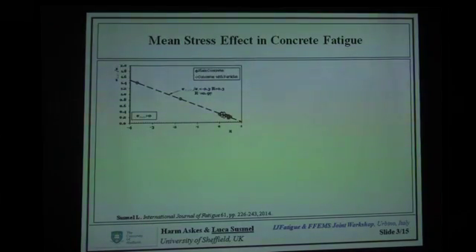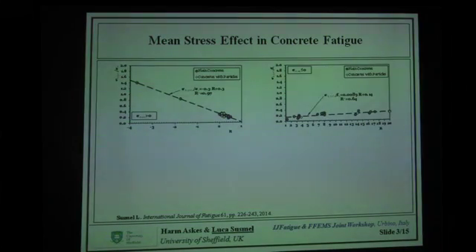If you start considering the high cycle fatigue behavior of concrete and you plot the amplitude of the endurance limit normalized by using the corresponding reference strength, that is tension or bending under tension and bending, or the static strength under compression, what you see here is that there is a clear mean stress effect. This is true under either tension or bending. But this is also true, slightly less evident, under compression.